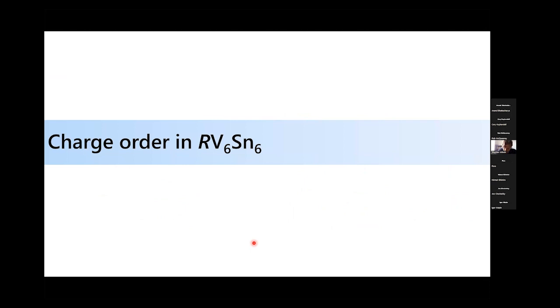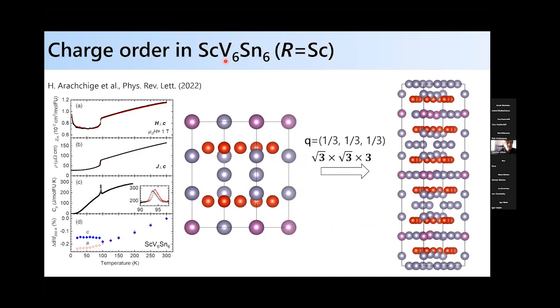Switching briefly to discuss charge orders. In the YV6Sn6 system, as I showed you, it's a non-magnetic system. It also doesn't realize any electronic instabilities that we can tell. But David Mandrus's group showed that if you put scandium in place of yttrium, then below about 100 Kelvin in the susceptibility, resistivity, and heat capacity, there's a phase transition consistent with the onset of charge order.